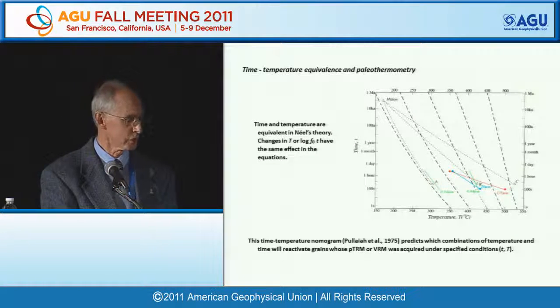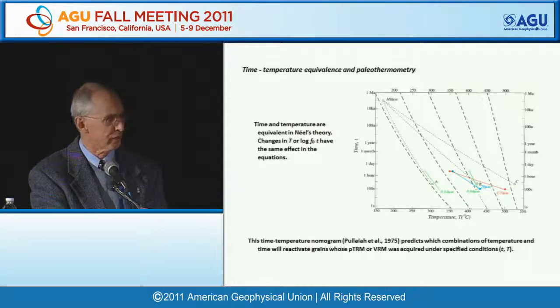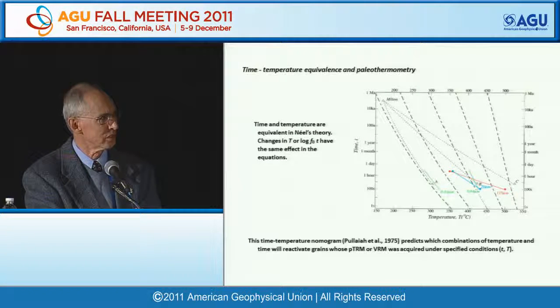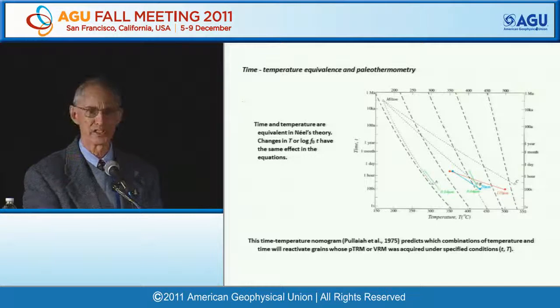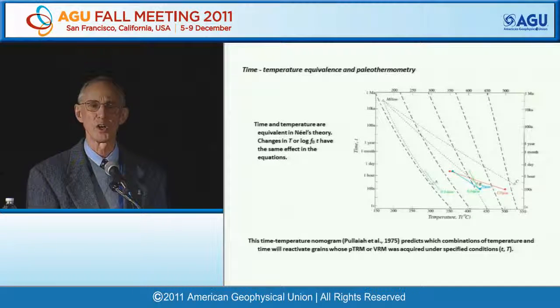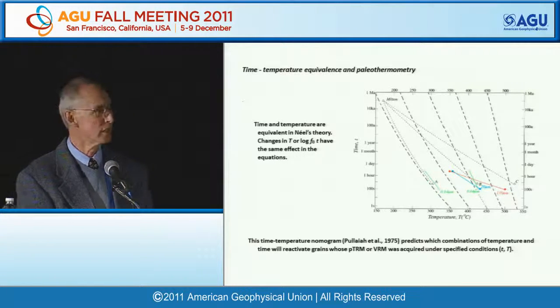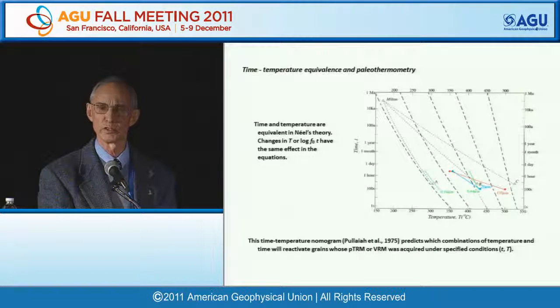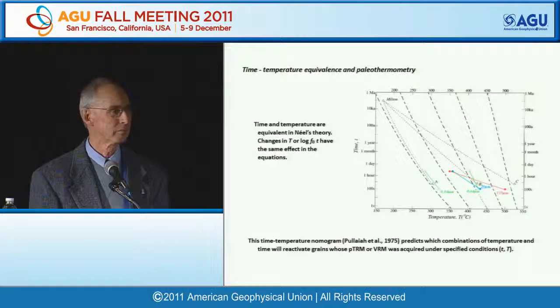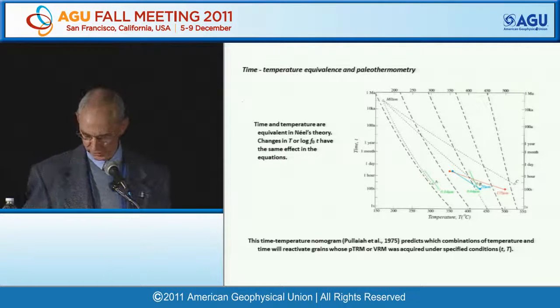When you look at larger grains, however, 20 micron grains, 135 micron grains, or at non-single domain samples from rocks, then you get results that cut sharply across these theoretical contours. You have to go to much higher temperatures. A thermal demagnetization tail, not predicted by Néel theory.